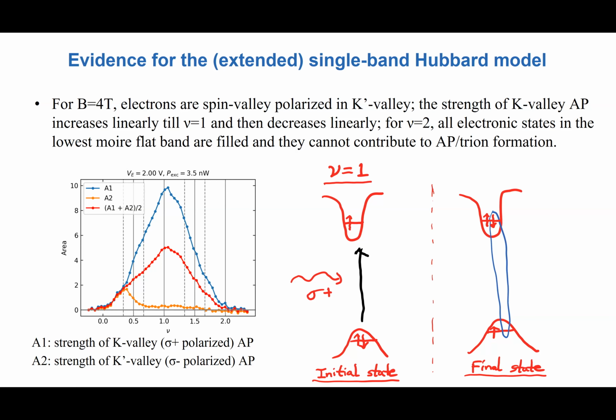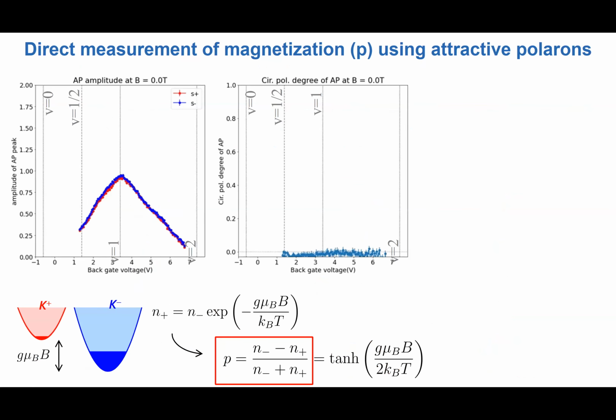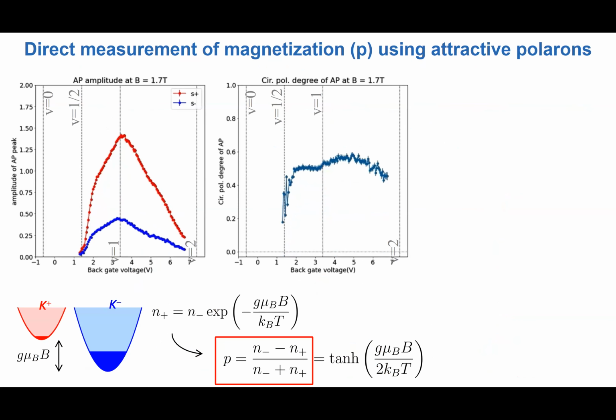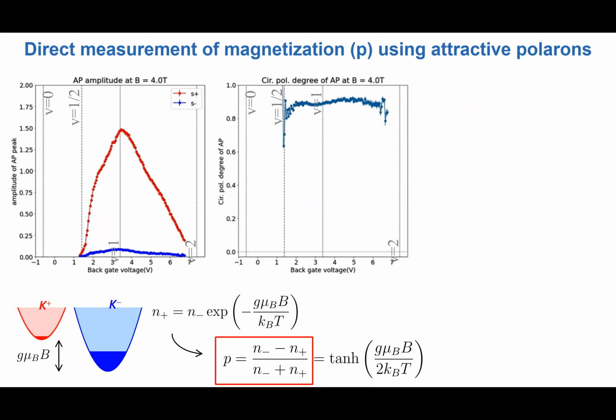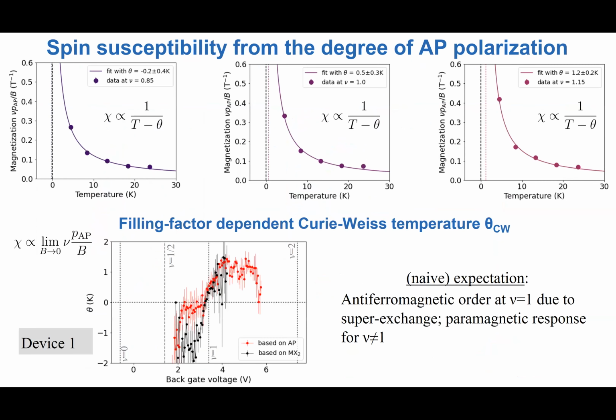The other guy picks up and then goes down because the states are no longer there. Okay, so it's picked up. So this is then how the sigma plus and sigma minus oscillator strengths evolve. And from these, we can use the magnetization at various temperatures and fit this to a Curie-Weiss law to determine a Curie-Weiss temperature, to get an idea about when we can expect to see interesting magnetic phenomena.